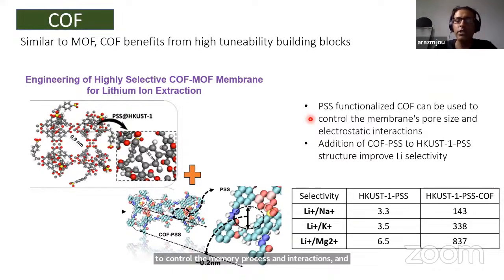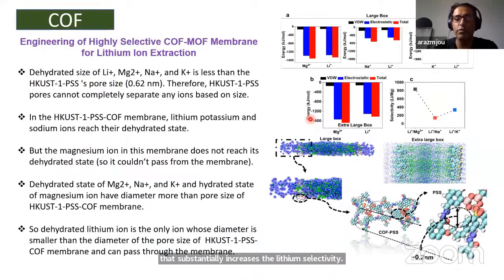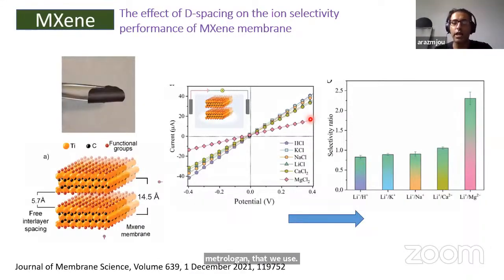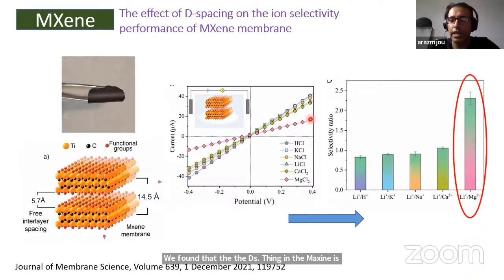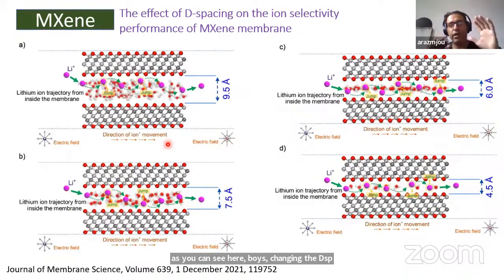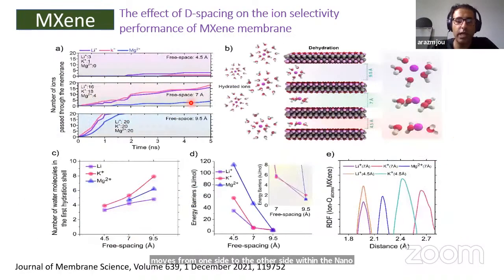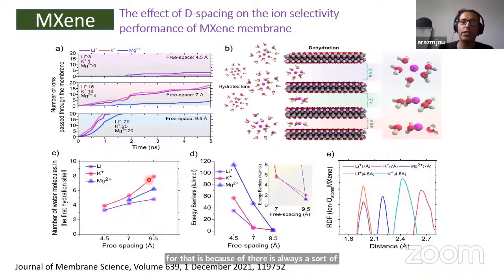So MXene was another type of material that we used. We found that the D spacing in the MXene is critical in rendering the lithium selectivity to the membranes, and then found that the selectivity ratio can increase to 2.5 substantially by altering the D spacing of MXene membranes. And as you can see here, by changing the D spacing, we can control the way lithium ion moves from one side to the other side within the nanochannels. The reason for that is because there is always a competition between the energy barriers within the nanochannels of MXene.